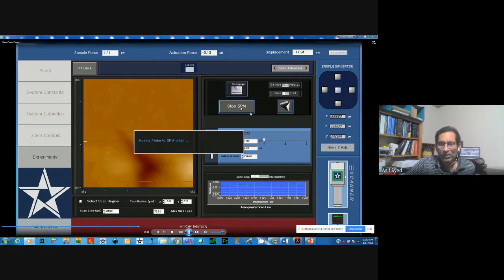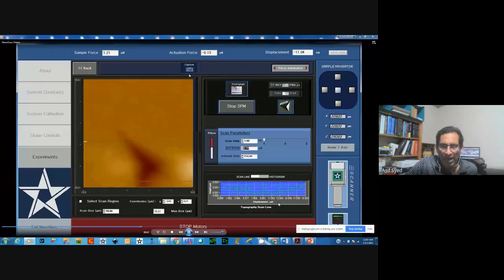Now when you engage and start the image, this window will pop up, and it will start to image from the bottom to the top. You can see it line by line. You can see the line profile here. As it images, you can see the image profile line by line, and it is constructed to give you the 2D image of the surface. Now it is scanning from the bottom to the top. This is a 10 by 10 micron size image. No, sorry, 20 by 20 micron size image.